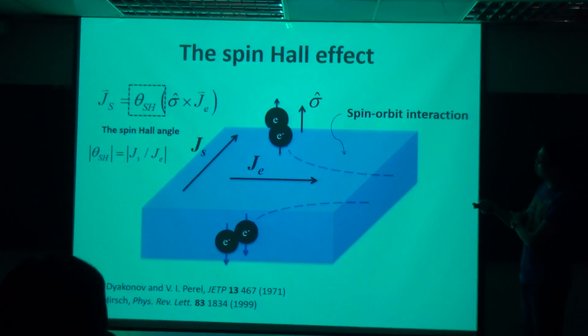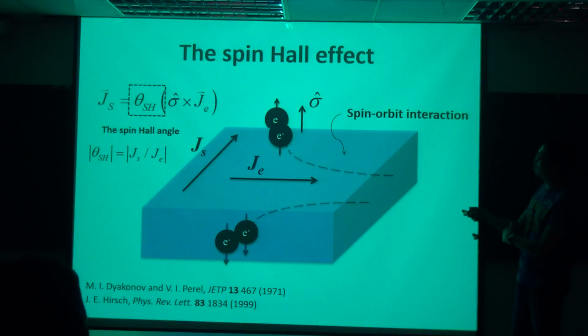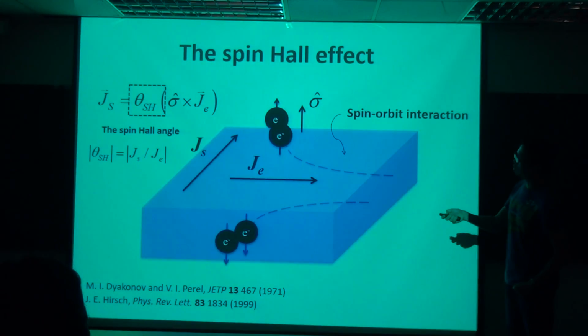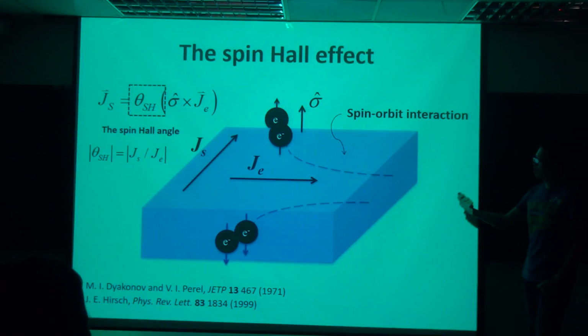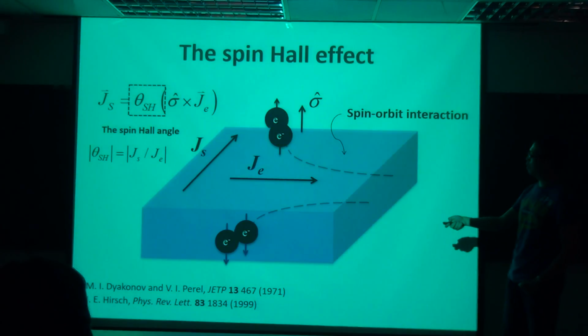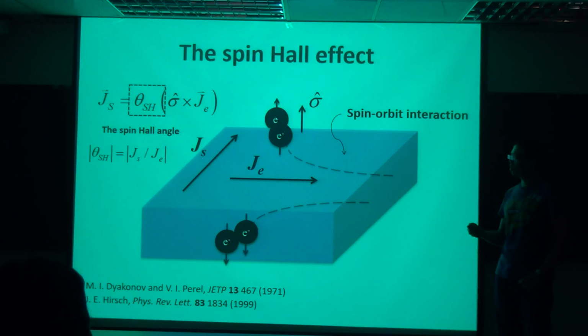And more importantly, the strength will be characterized by this spin Hall angle. Although nowadays we typically call this the spin Hall efficiency or spin Hall ratio, because this is actually a tangent theta. But nowadays we know this value could be really large, so it's not really correct to call this an angle anymore. But anyway, just consider this as a parameter, and if you take the magnitude, the absolute value of this is just the ratio between spin current and charge current. So you can consider this as the conversion efficiency from, say, charge to spin. So the larger the better.